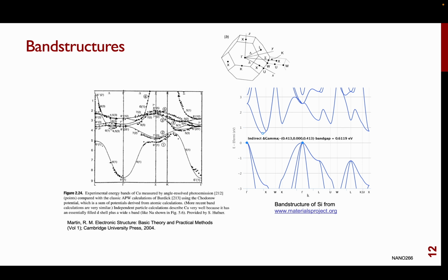Okay. Again, this is silicon. So if you go to the Materials Project, you actually see the exact same plot. Things like your band gap will be significantly underestimated, but generally the features of the band structure still seem to be reasonably well described. Okay, so in other words, if you are calculating things like the effective mass and the general features, for example that it has an indirect band gap, all these features are well reproduced. It's just that the size of the band gap itself is wrong.